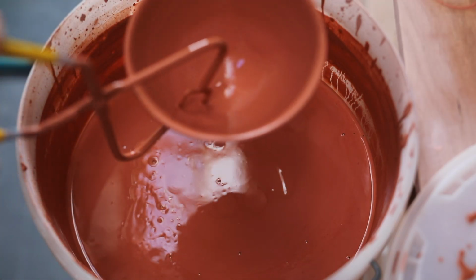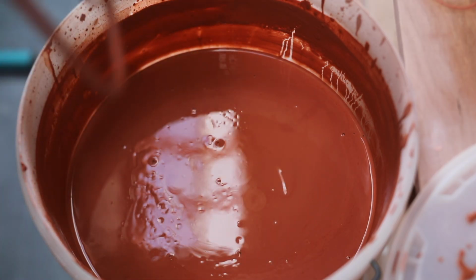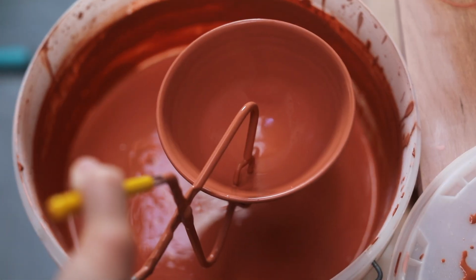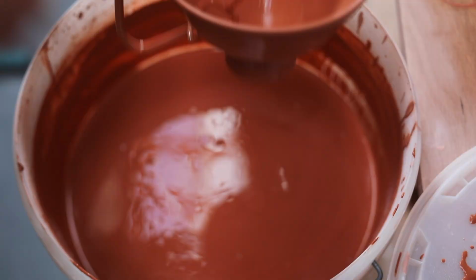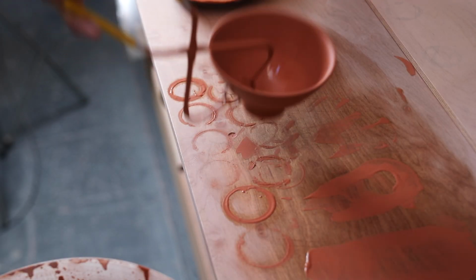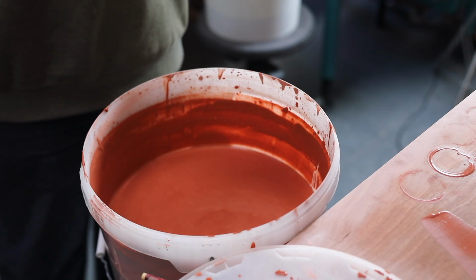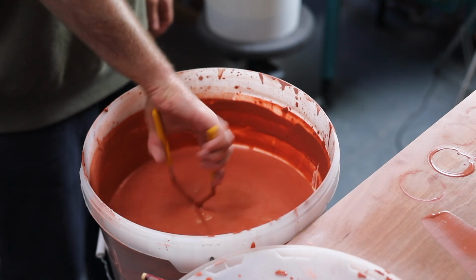You can hear me blowing on the pot, and I do this to pop any bubbles that come to the surface, as if I do this now they often pop and heal over, creating a flush surface, whereas if I don't get rid of them at this point, they just create these tiny craters which I'm going to have to tidy up later.